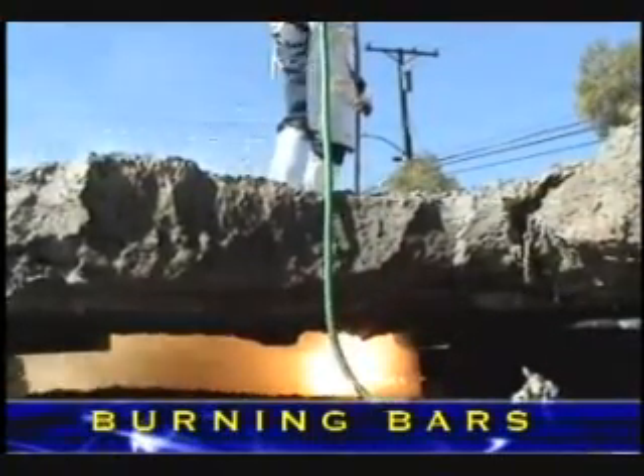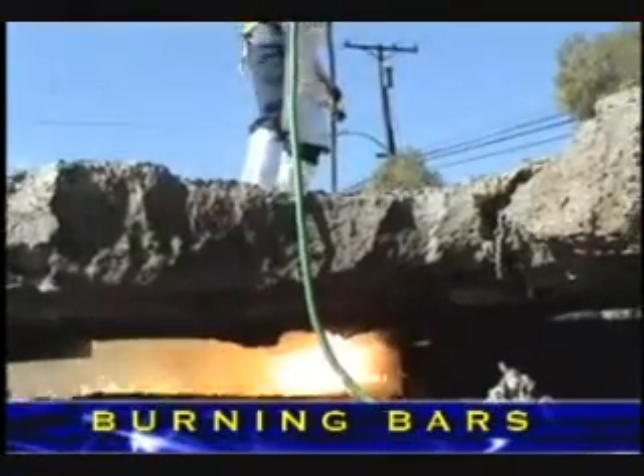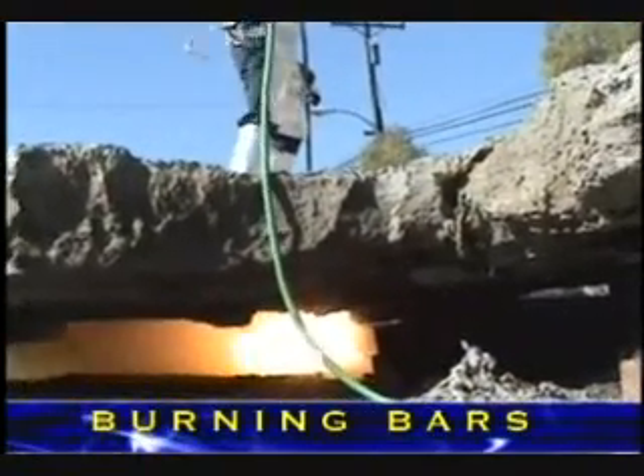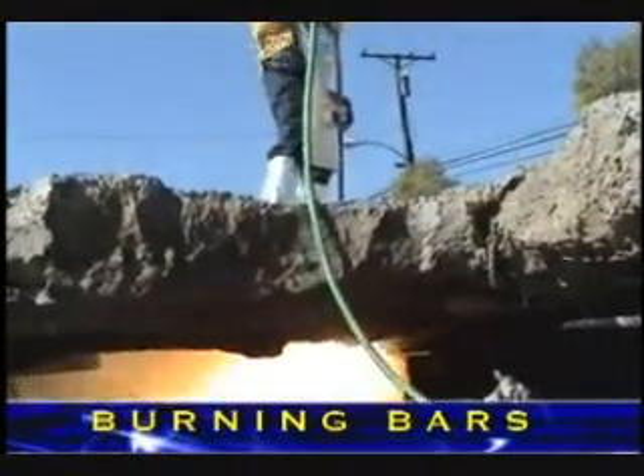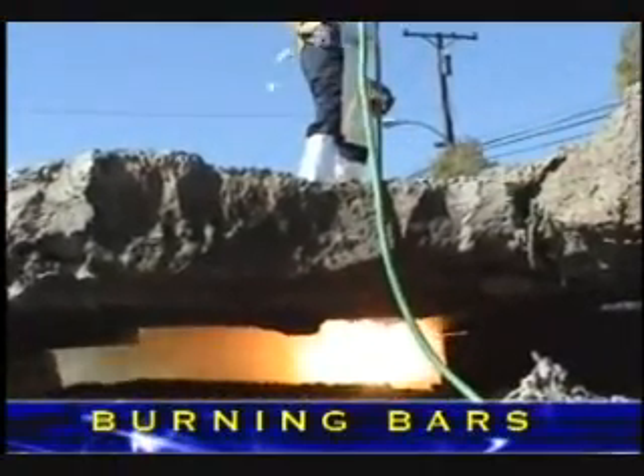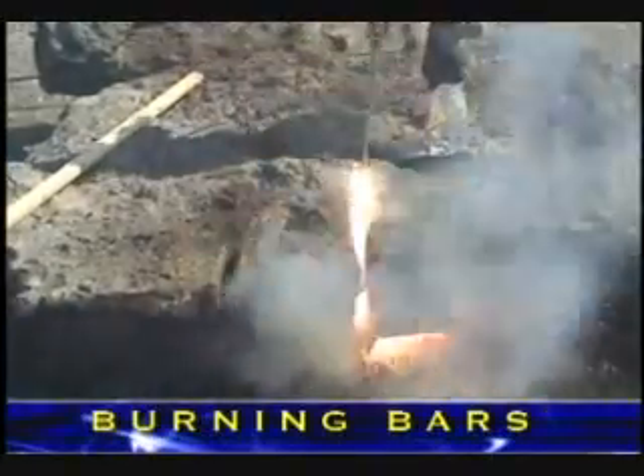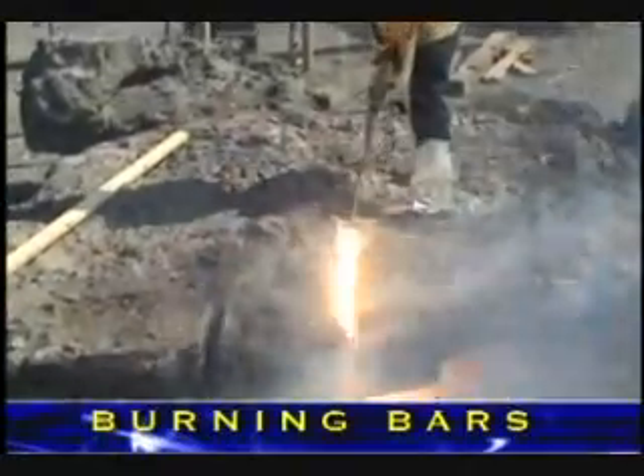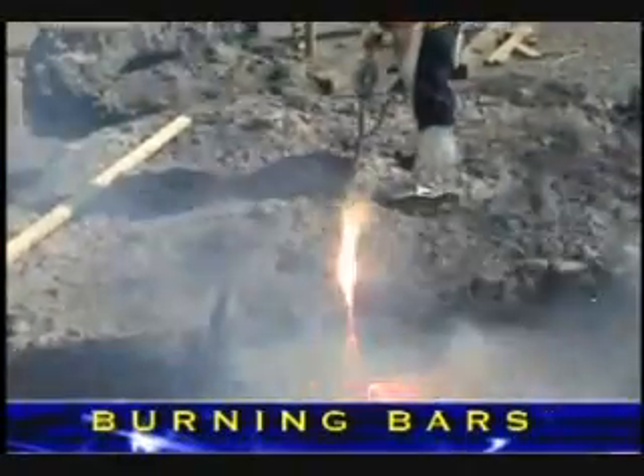Materials such as aluminum and titanium cut rapidly and produce very high heat. The operator in this case is cutting up aluminum waste at an aluminum foundry. The material ranged from 10 to 16 inches thick and contained a lot of refractory and slag. The cut rate on this material was 3 inches per minute.